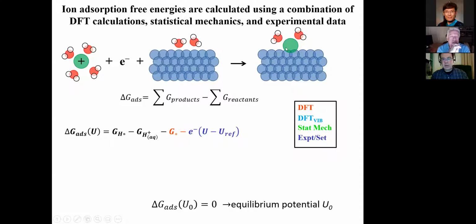I know where to put it. I can put hydrogen on the surface and ask if it wants to adsorb on an atop site or a hollow site, but also I might be worried about how that's solvated by water. So to do a first approximation, we might neglect that solvation, but we're going to calculate the energy of hydrogen on the surface, bare surface, and the proton in water.